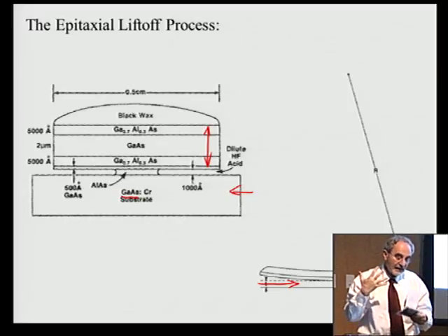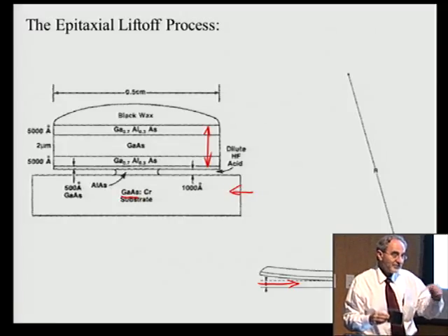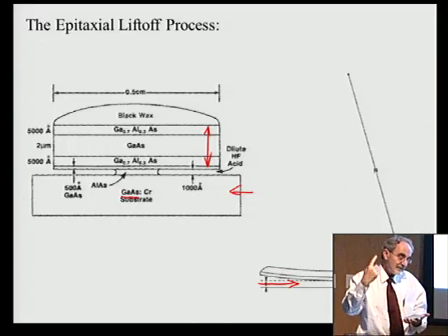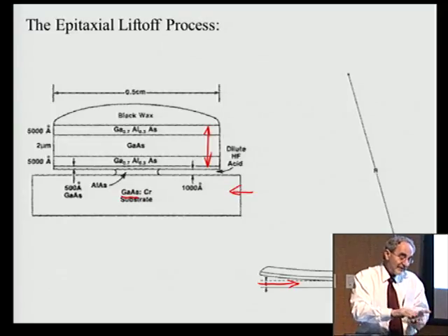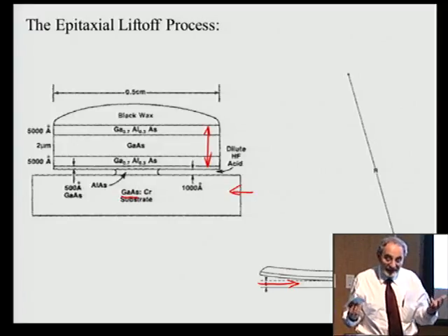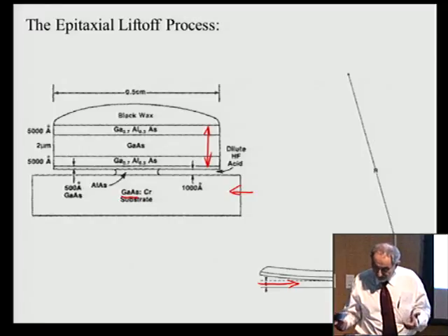Now, ask what told us that we were going to break the record. The key step was getting the film off the substrate, because substrate quality is never as good as epi film quality. So as long as the solar cell was sitting on the substrate, you could never get the photon recycling and the photon re-emission, because the photons would just disappear into the substrate. And so the instant we peeled the solar cell off the substrate, the voltage immediately started going up. And then I looked back at the theory we had done, and the theory had already anticipated it. So that's the key thing.